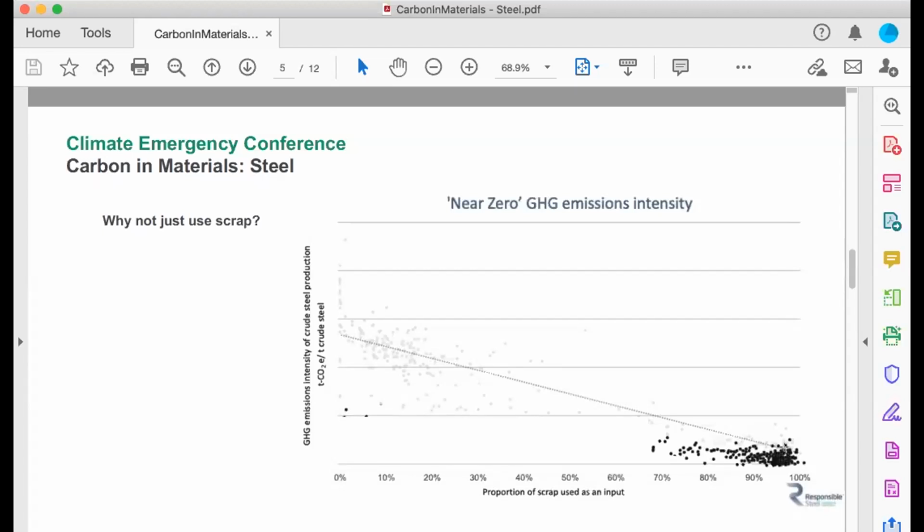In terms of scrap, the more primary metal that goes into the stock, the greater the opportunity for using scrap. So the proportion of scrap used goes up somewhat, but not massively, to around 55% by 2050, but certainly not enough scrap to meet projected demand, even in that sustainable development scenario. To add to that, the emissions from making steel from iron ore are so much greater, so that when you look at the total emissions over that time period, from now until 2050, you're looking at 80%, 90% of emissions coming from iron ore.